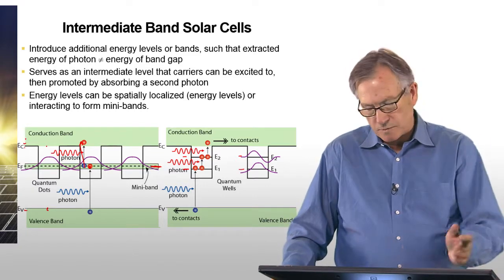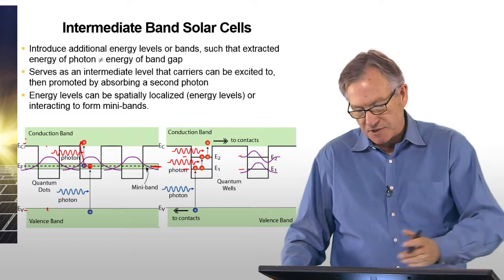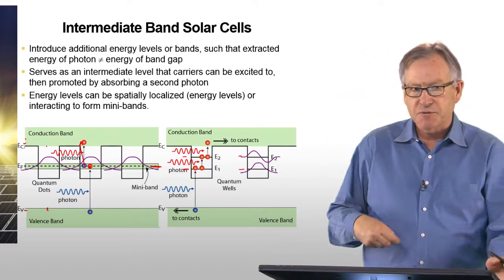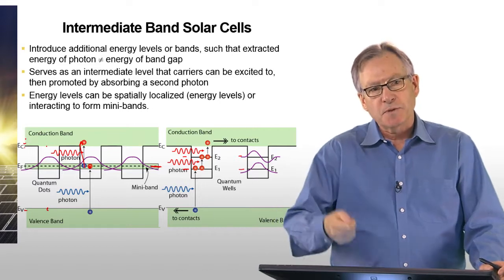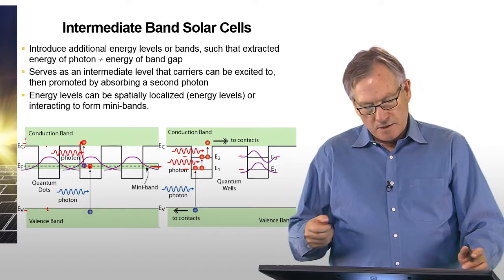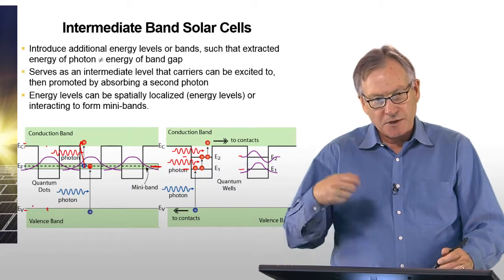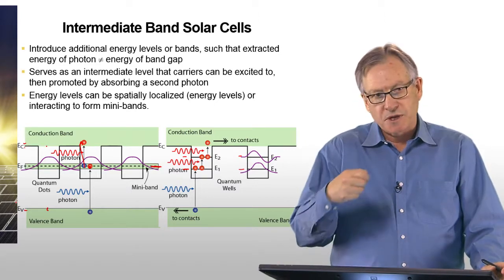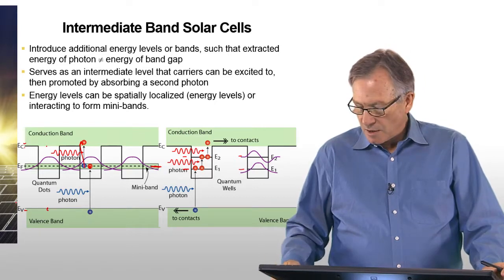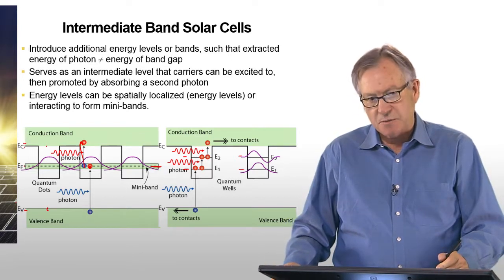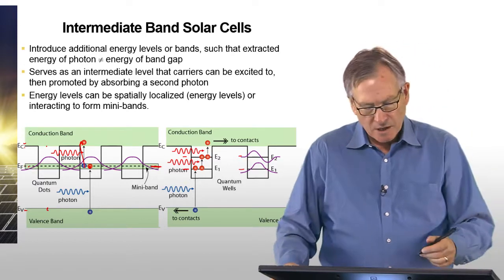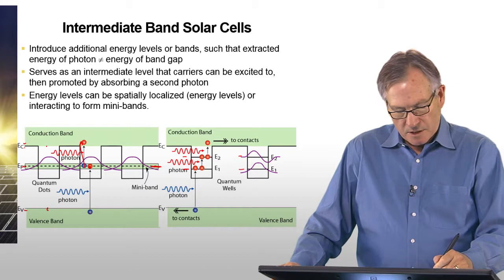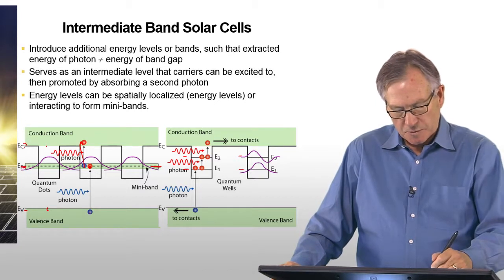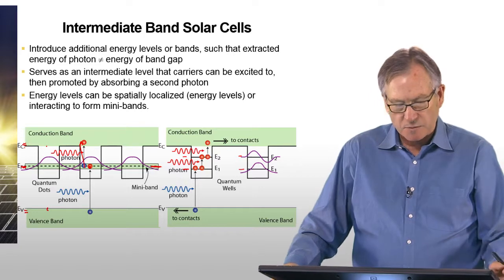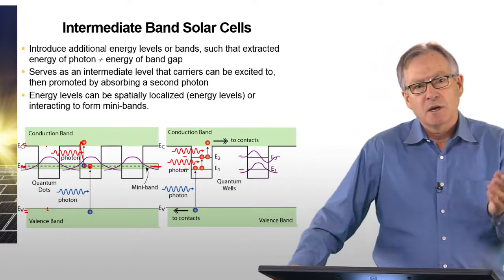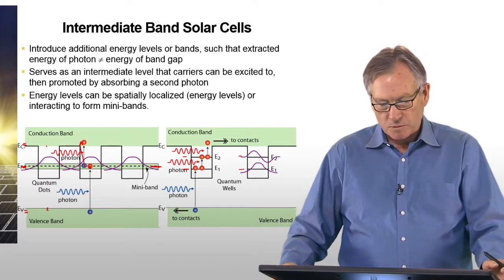This, of course, depends on many things having to happen simultaneously, and to date, practitioners in the field have not successfully improved the efficiency. They've come close to realizing the efficiency of the material without the intermediate level, and all signs point to at some point being able to demonstrate this. But in any case, there are several things that have to happen simultaneously, and one is that this level has to be out of equilibrium with the electrons and holes in the conduction and valence band, which is practically hard to achieve because of the microscopic scattering processes that I talked about before.